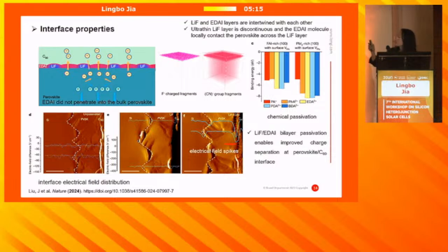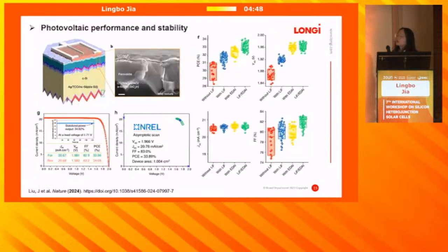We can see that after we insert this bilayer interface, it exhibits electrical field spikes here. So this interlayer can form a built-in field at this interface, by this interface dipole, which can facilitate the charge transfer and improve the charge separation at the perovskite and carbon-60 interface. So we used this bifunctional layer to construct perovskite-silicon tandem solar cells.